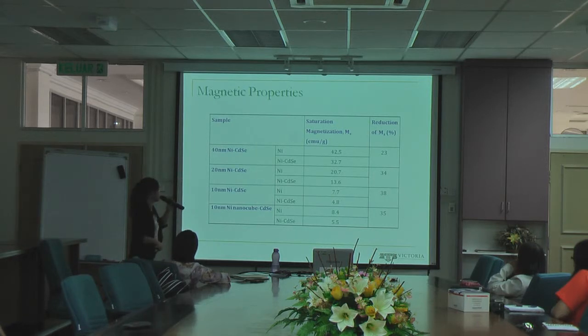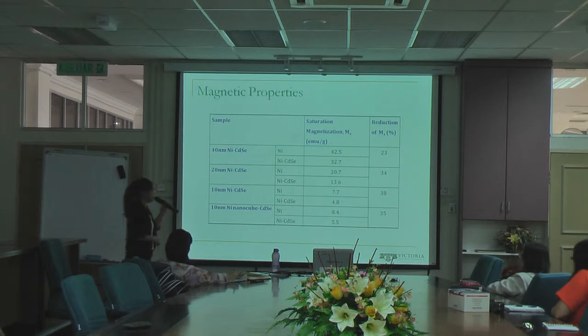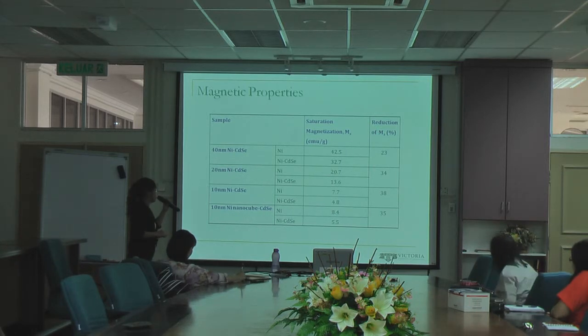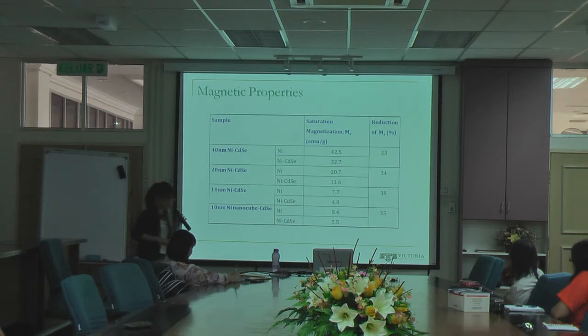So I'd like to relate this a bit to the previous literature. With the composites I have prepared, I was able to reach the highest value of magnetization of about 32.7 emu per gram.